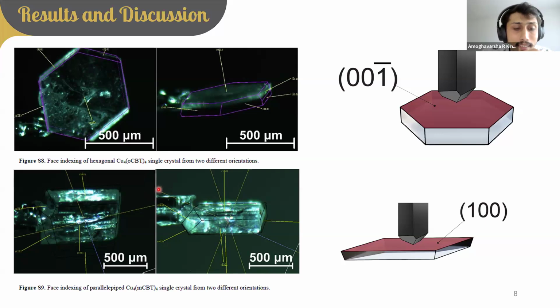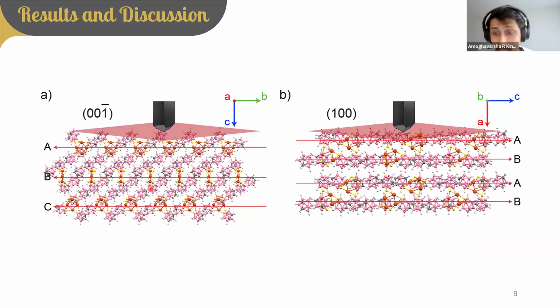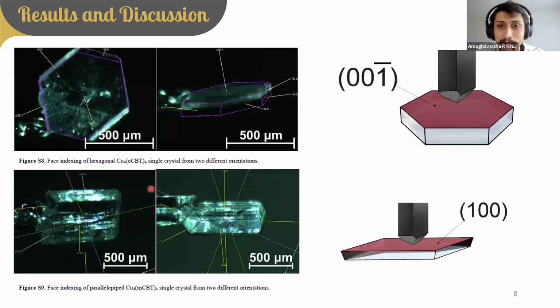For that, I can answer that whatever moduli we get for a material is comparable to the bulk modulus as well. Did you understand? Like the whole material. You can even test it in our lab itself without measuring it. Take a spatula and just put some pressure on both Cu4(oCBT)4 and MCBT crystals. You can see that Cu4(oCBT)4 is slightly more difficult to break than Cu4(mCBT)4 crystals. We have seen that after measuring this also. So the bulk modulus is similar to what we get from nano indentation.